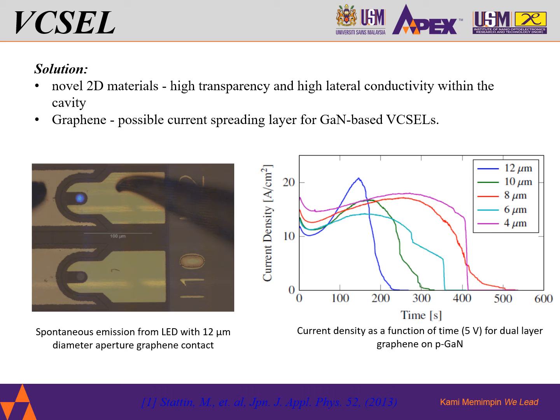Graphene is one of the possible current spreading layers for the GaN-based VCSEL. As you can see here, this is a spontaneous emission from an LED with a 12 micrometer diameter aperture graphene contact. As a result, across the dimensions of 4, 6, 8, 10 and 12 micron, the current significantly increased from 10 to nearly 20 ampere per cm squared. This is for the dual layer of P-GaN.